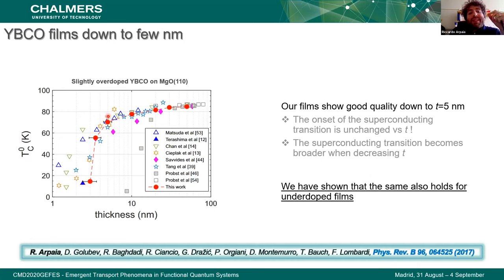And what we observe is that down to 5 nanometers, basically our critical temperature, the zero resistance critical temperature, is in perfect agreement with the best result that people achieved a long time ago when sandwiching YBCO between two layers of PBCO. Well, in our case, instead, YBCO is not sandwiched by this seed and capping layer. And these properties also hold for underdoped films.